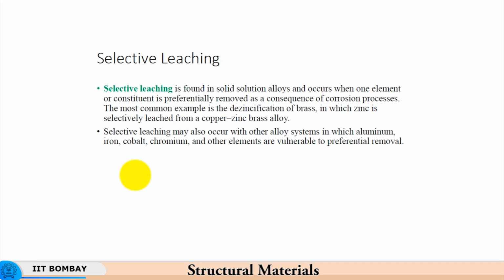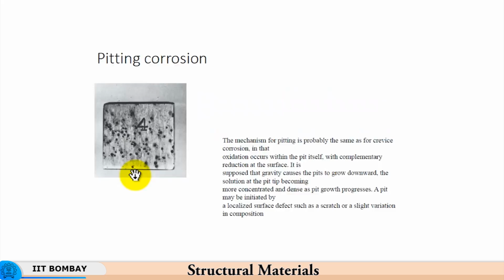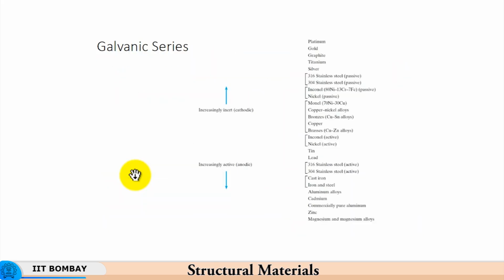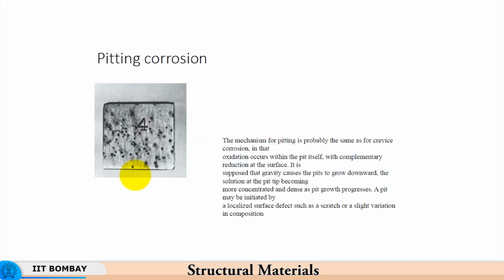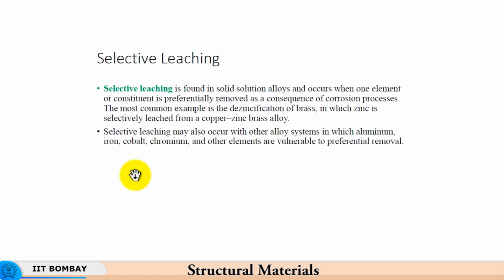This is typical in brass type of alloys, where you have what is called de-zincification of brass. You know that 70-30 brass, for example, is 70% copper and 30% zinc, but this zinc can get selectively leached out from copper. If you look at the electrochemical series we saw earlier, you have copper over here and zinc over there. They are far away from each other, and zinc is much more anodic compared to copper. Some zinc is dissolved in copper, and the rest remains, so you have a loss of zinc to leaching. Zinc is much more chemically active, it is more anodic, so it can selectively get dissolved.